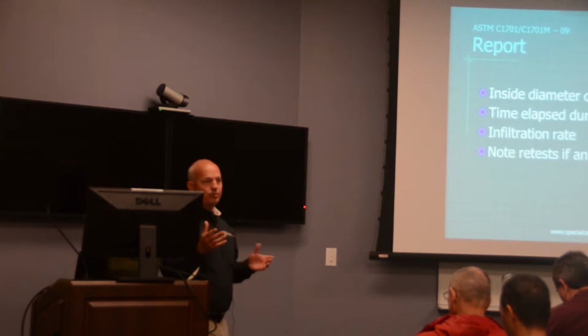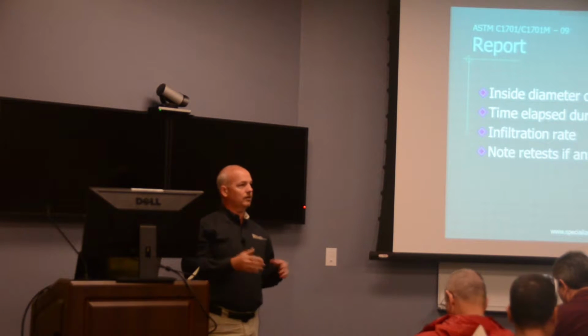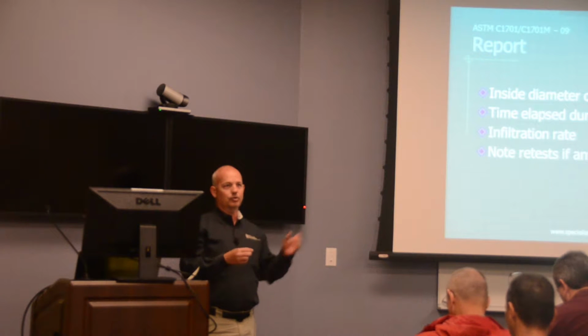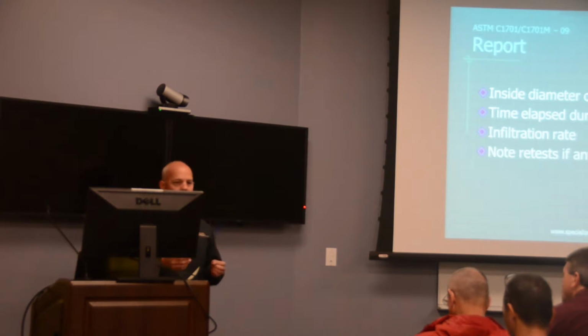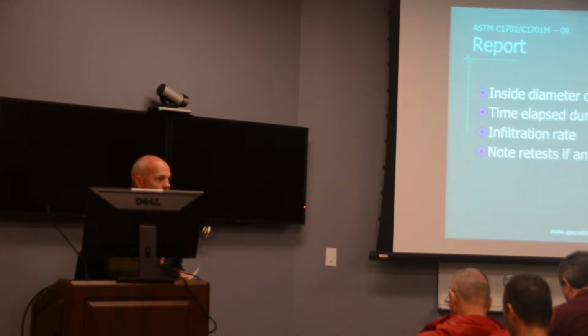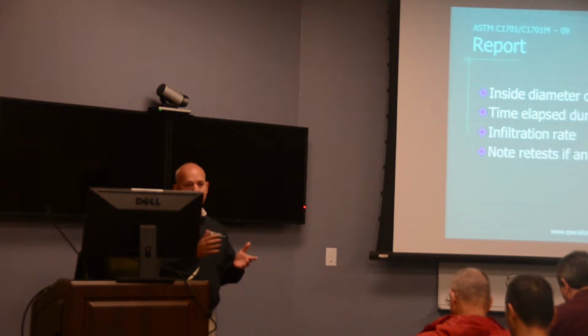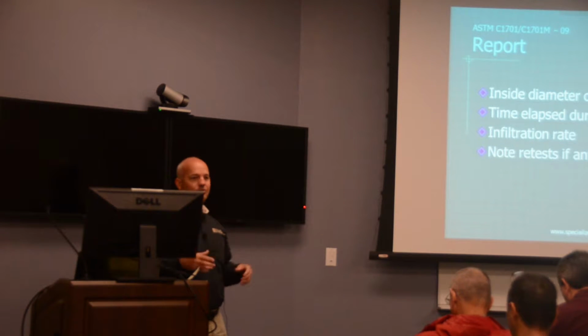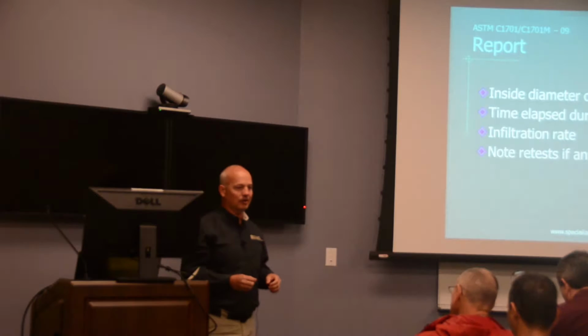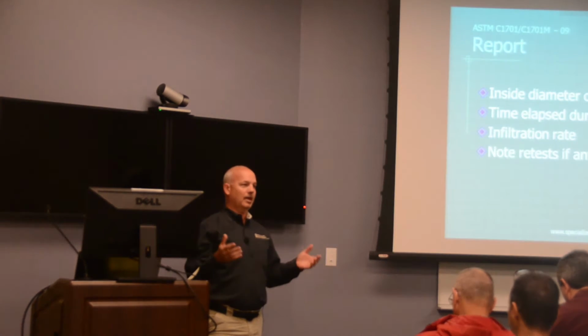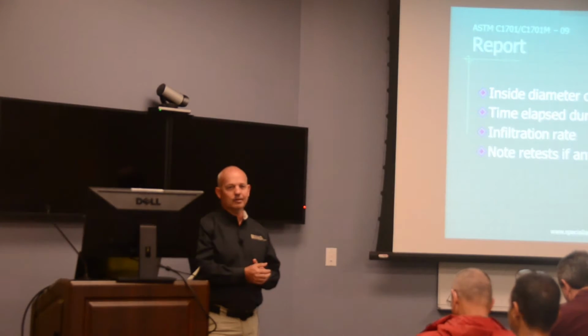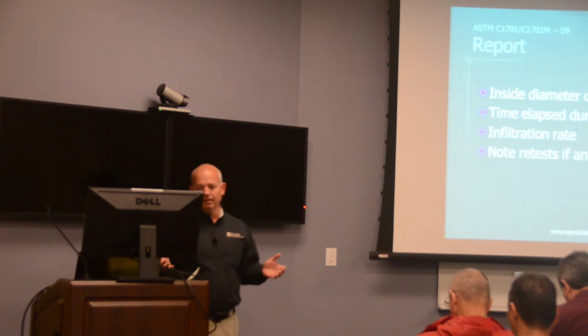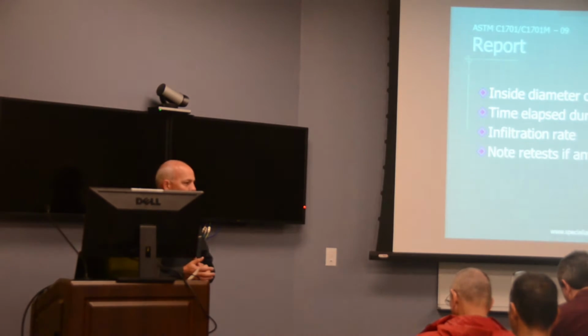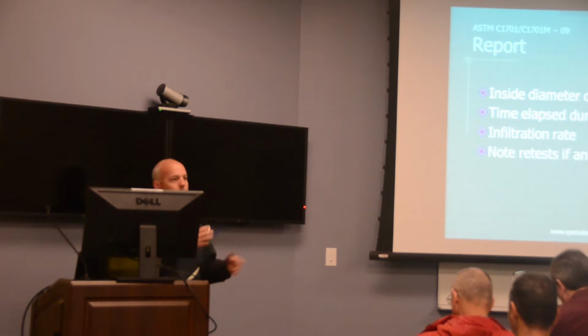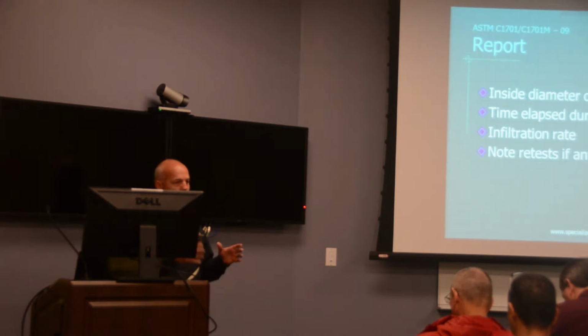Initially, the project's about 3 years old. We did initial tests, and then we did some cleaning, which you'll see how they do the cleaning, and then we redid the test. And as you can see from the results, in one area, the test number 1, we quit the test after 10 minutes because the water was just barely seeping into the concrete. It was probably as clogged as a clay. It was acting like a clay. And after cleaning, it was 143 inches an hour. So the cleaning process works really well for a clogged surface.